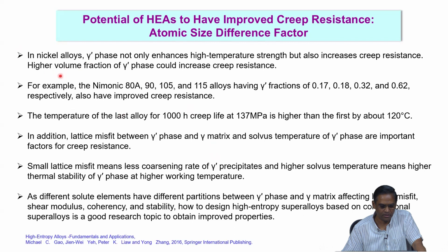In nickel-based superalloys, gamma prime phase not only enhances the high temperature strength, but also increases the creep resistance. And of course, the variable is the gamma prime phase fraction. Higher volume fraction could increase the creep resistance. For example, if you take the Nimonic series, alloys 80A, 90, 105, 115, they have gamma prime fractions of 0.17, 0.18, 0.32 and 0.62 respectively, and also have improved creep resistance.